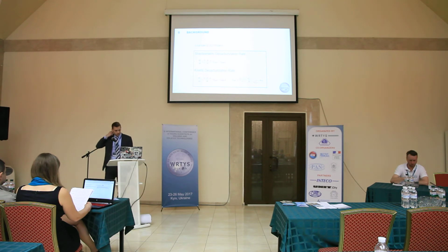Here is also some background information, an example of the VOD process. What you see here is the difference between stoichiometric decomposition and kinetic decomposition. Because when you blow oxygen on the liquid steel, first of all, the elements get oxidized by just a stoichiometric approach, where, let's say, aluminium and titanium directly react with the oxygen that you blow onto the steel, and then when the system gets into a specific condition, the kinetic approach takes over from the stoichiometric approach.